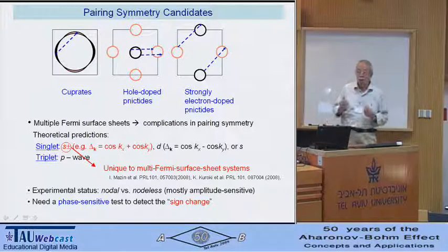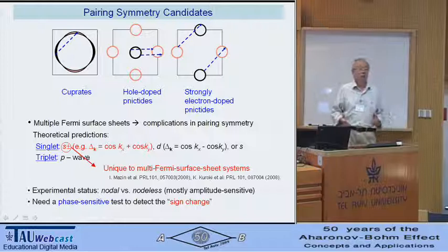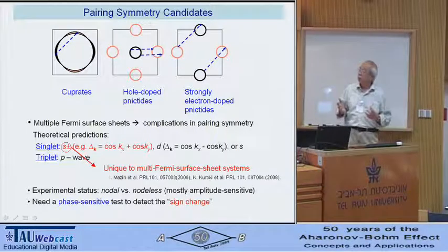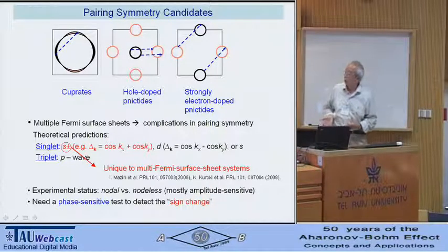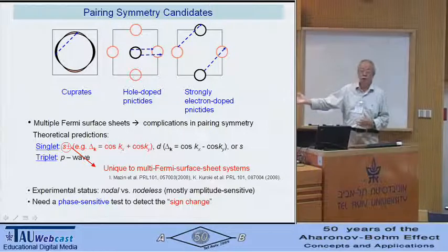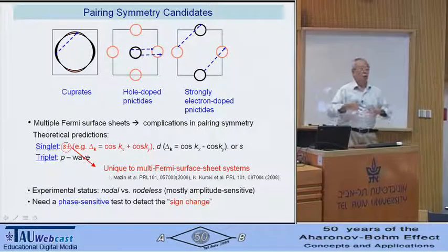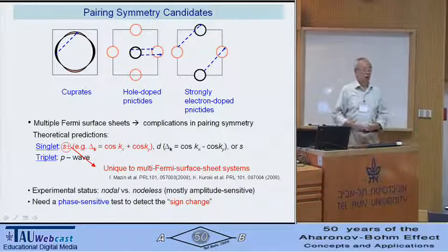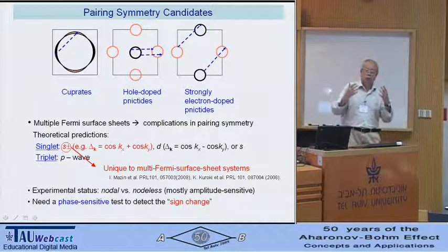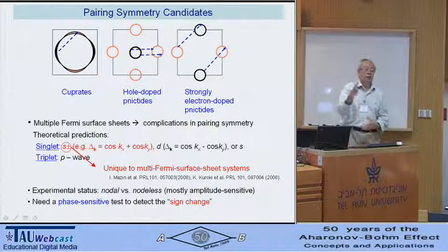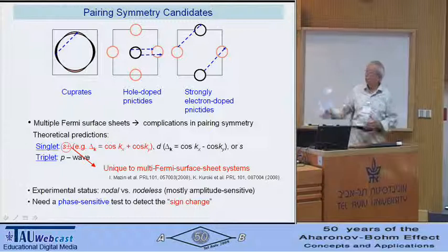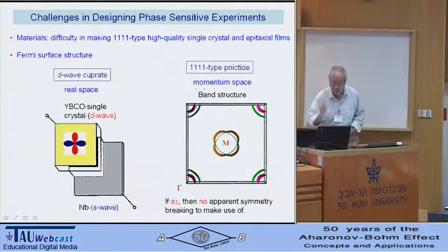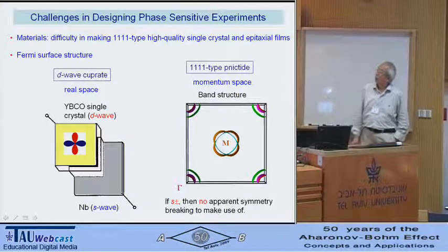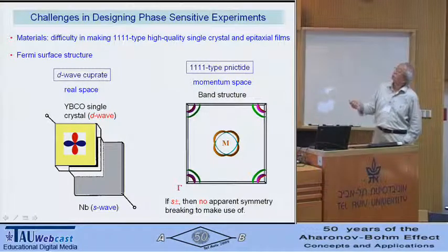Okay. Now the current status right now is there are lots of experiments trying to figure out what the pair symmetry is in these new materials. However, most experiments are amplitude sensitive. In other words, they measure the amplitude of the pair wave function, not the phase. So that's why it's model dependent. It's difficult to pin down unambiguously what the pair symmetry is. So you've got to use a phase sensitive experiment. That's what I'm here trying to present. And here, I want to mention the challenge in the design of such a phase sensitive experiment. The reason why is this.